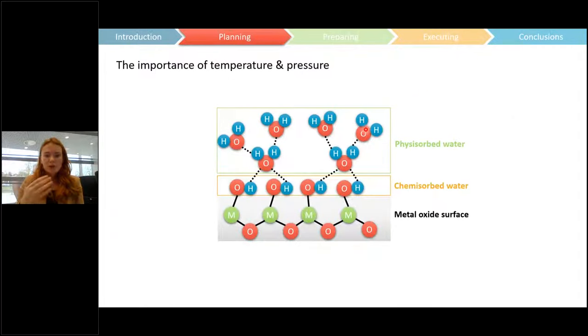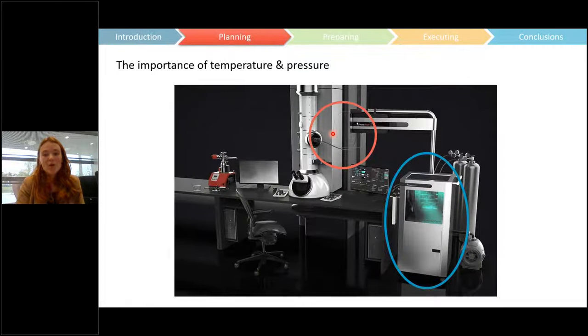So where does this water come from? The first thing is it could be coming from our sample itself. It's highly likely that we have water in a physisorbed and chemisorbed state on the surface of metal oxides, on the surface of our materials, and it's really important, therefore, to remove this water through a drying step at the beginning of our reaction, before we even do anything. So that was our first theory, but the second place that you can see water is, of course, from leaks.